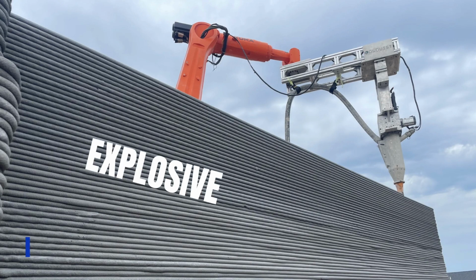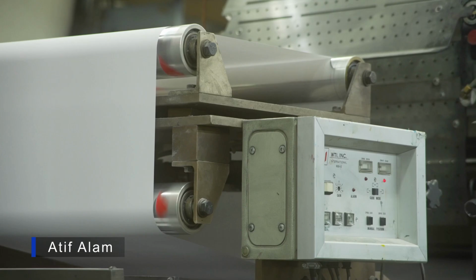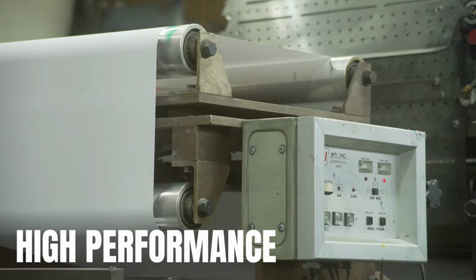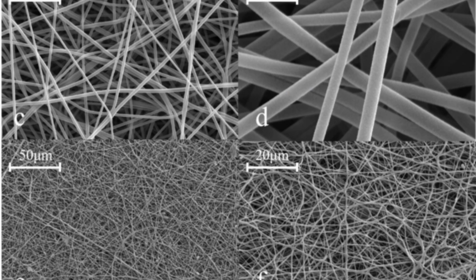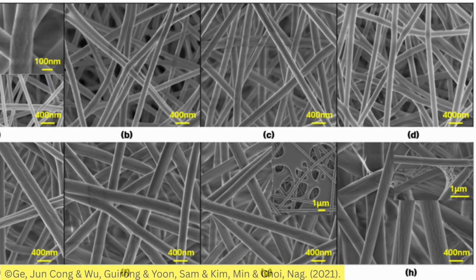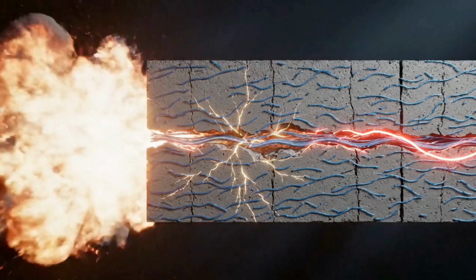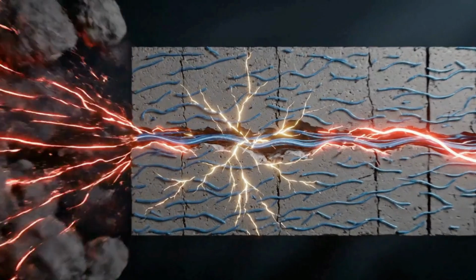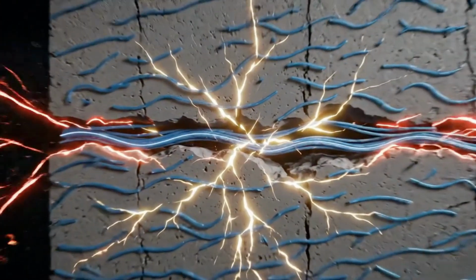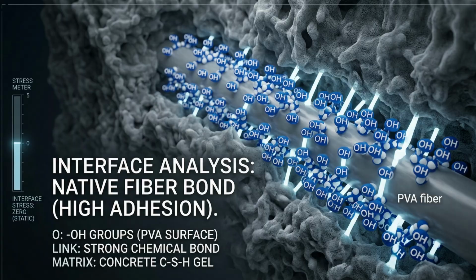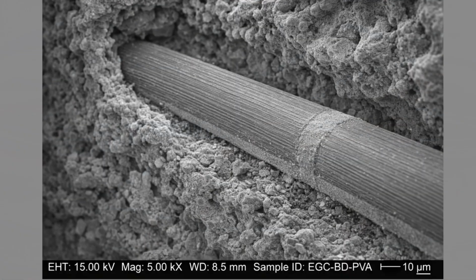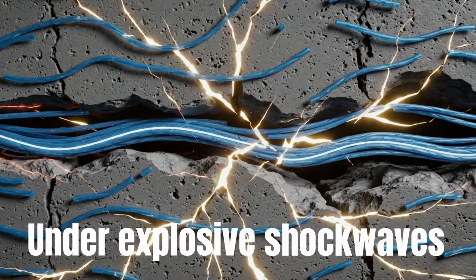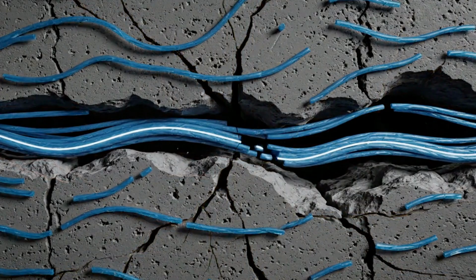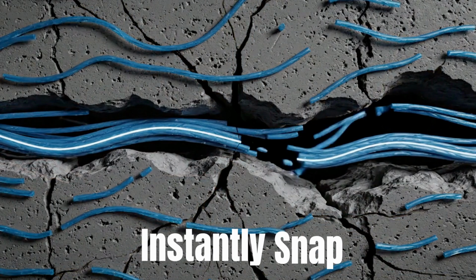To achieve the required explosive resilience, our proposed design disperses high-performance PVA fibers into the dense matrix during the final mixing stage. These specific fibers feature an elongation capacity of 6%. When a blast wave impacts the structure, extreme stress initiates tiny microcracks. Naturally, PVA fibers possess hydroxyl groups on their surface, creating an incredibly strong chemical bond with the concrete. But under explosive shock waves, this bond is actually too strong, causing the untreated fibers to instantly snap.